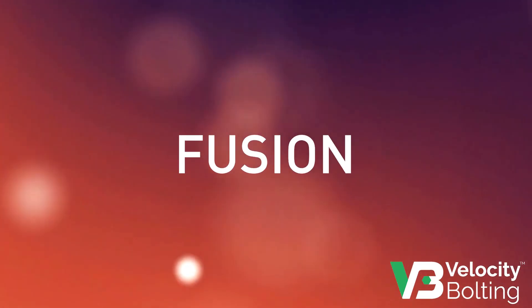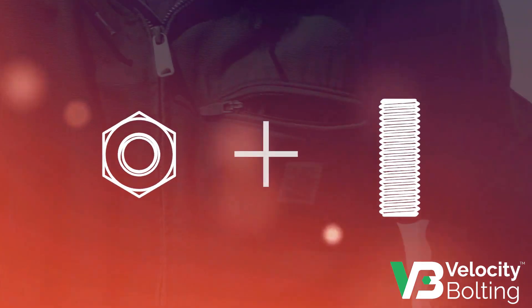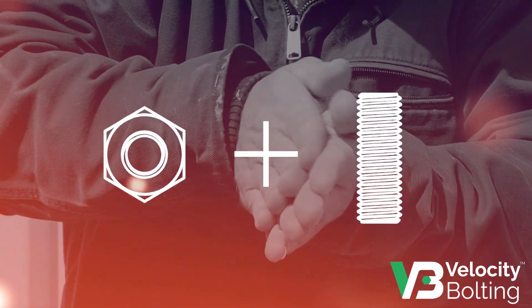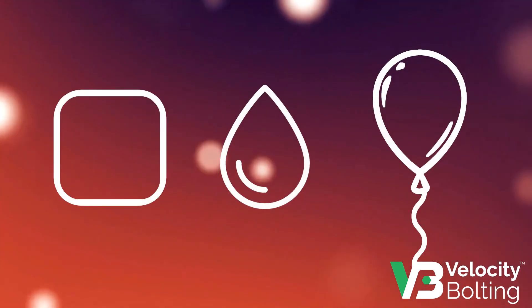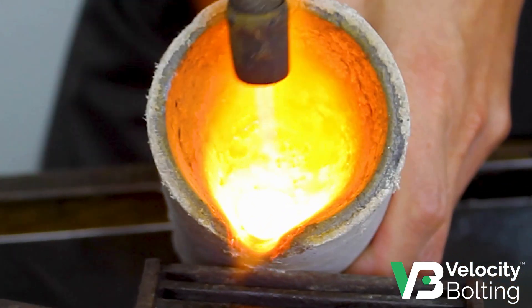Fusing into one part is exactly what happened. However, the nut and bolt didn't melt together from friction and heat like a friction weld. Galling isn't a result of phase change because nothing gets hot enough to enter a liquid state.